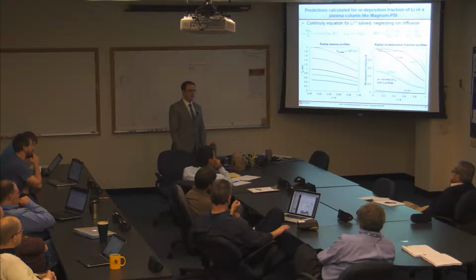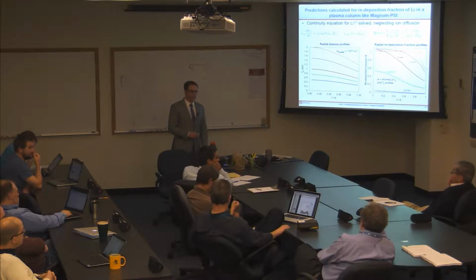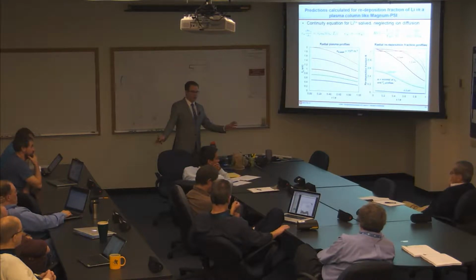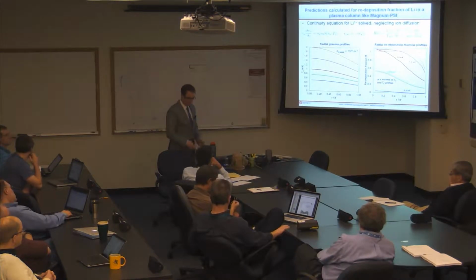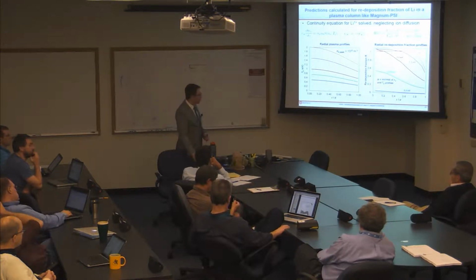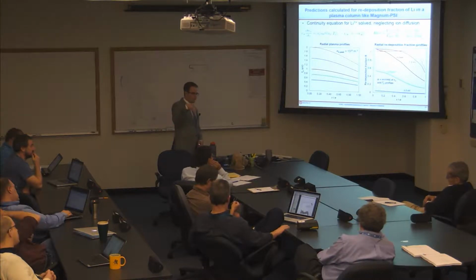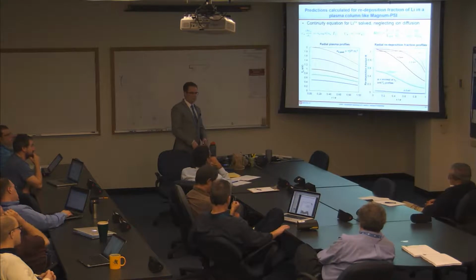Because the lithium atoms are eroded with a cosine distribution in polar angle. So it's including a neutral diffusion, in effect. They come off as neutrals. You're saying when they come off as neutrals, they reionize and come back down. Right. I mean, that's not really diffusion since there's no collisions going on, but it's modeling the streaming. It's a three-dimensional calculation, so geometric. Just the neutrals moving around. But then the ions only just follow the magnetic field line right back to the target.